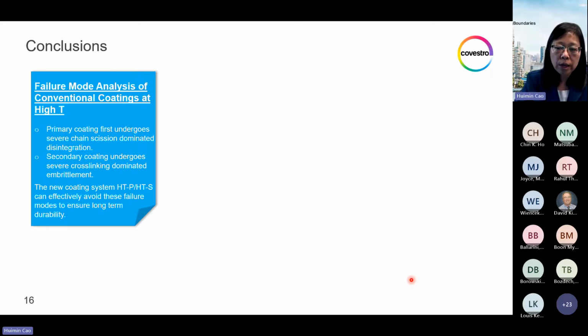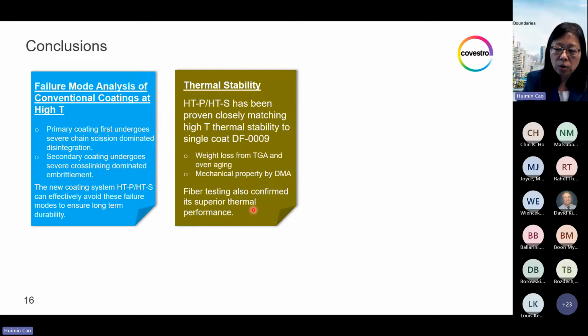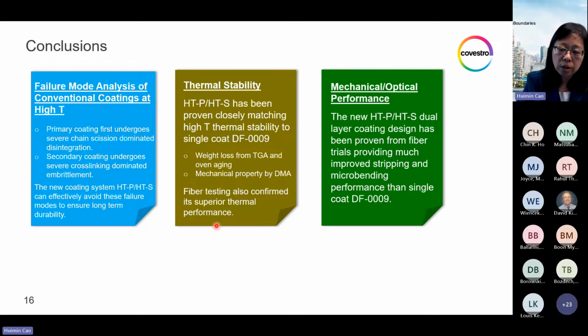So in summary, we have analyzed the different failure modes of conventional primary and secondary coating and designed our new primary coating to effectively avoid these failure modes. The thermal stability has been tested, closely matching single coat DF-0009 from film TGA and DMA tests, and fiber testing, which is not discussed in this paper, also confirmed its superior thermal performance at high temperature.